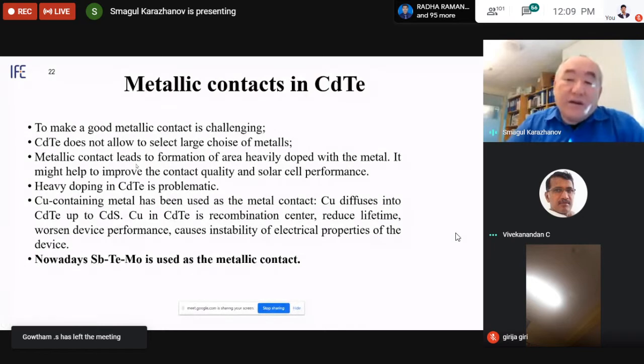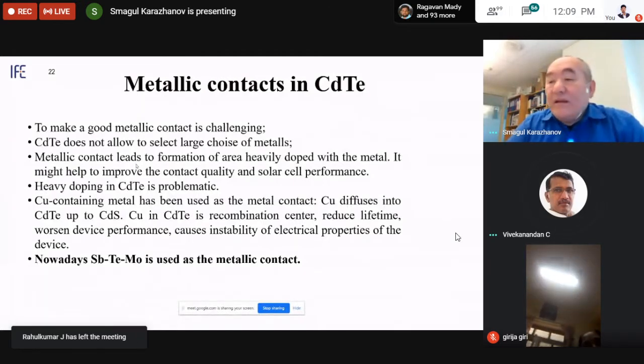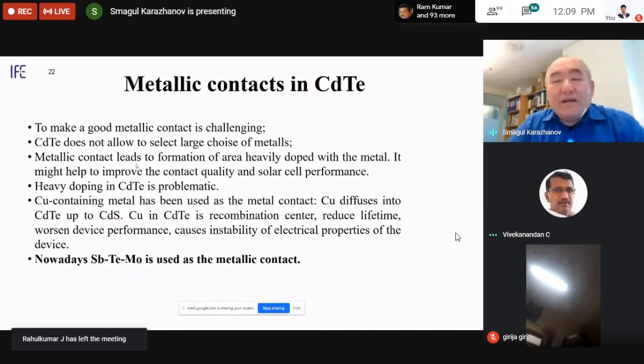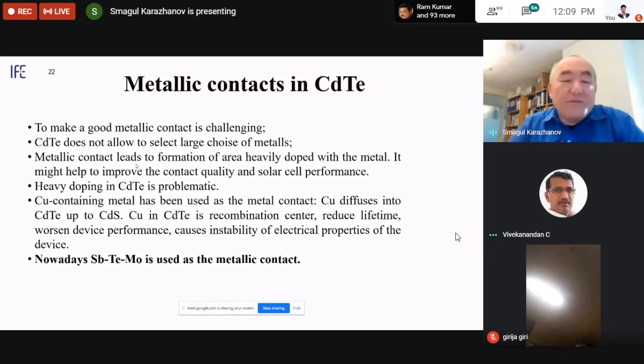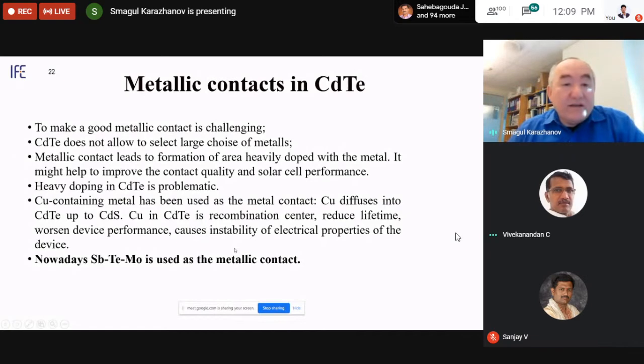And to make a good metallic contact to cadmium telluride is a challenge because it doesn't allow a large choice of materials. And upon using a metallic contact, a heavily doped region between cadmium telluride and the metal will be formed that will also influence the cell efficiency. Copper contact has been used, but then copper diffuses very fast inside cadmium telluride even at room temperature, and the copper provides a good recombination and that reduces charge carrier lifetime. So nowadays, antimony, tellurium, molybdenum-based metallic contact is used.